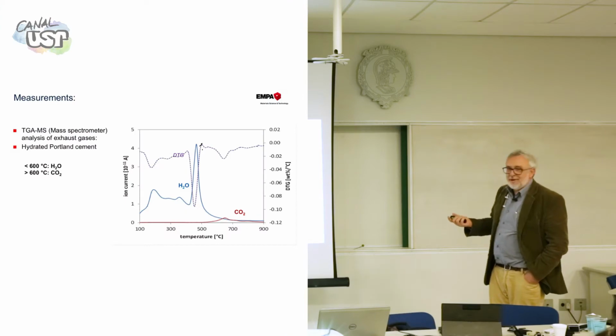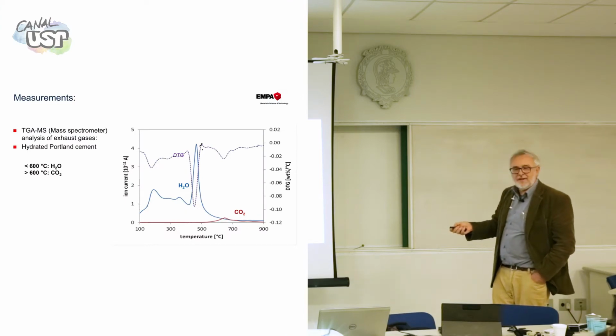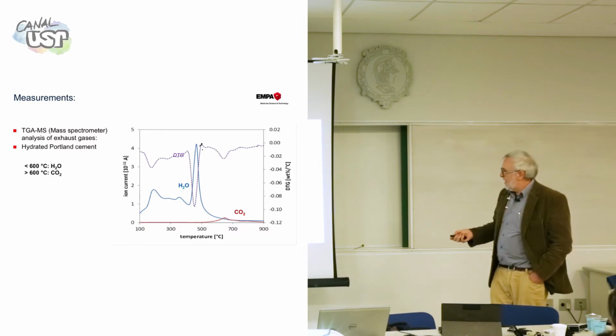So what we do in practical terms is say, okay, below 600 degrees centigrade, it's mostly water. And above that it is mostly CO2. Of course, this 600 depends on your sample size, how big your sample is, on your machine geometry, and exactly what you are talking about in terms of carbonates. What kind of carbonates do you have? Carbonation from accelerated carbonation is one thing. If you have a natural limestone that is millions of years old, it is another thing. So you have to look carefully at each sample.